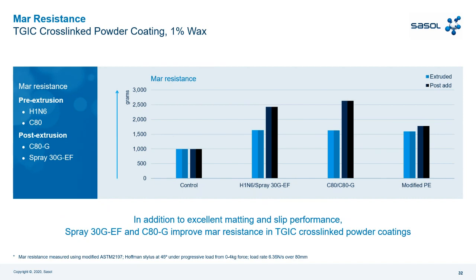micronized. Then in post-extrusion, we have Sasol Wax C80G, the micronized version of C80, that achieves a very high value, so means very high mar resistance. This is important for you. Then follows Sasol Wax Spray 30 GEF, that is the ultra-fine micronized version, a little bit less than C80G. So you can see here in the test that Sasol Wax Spray 30 GEF and Sasol Wax C80G give you a very nice result in post-extrusion.